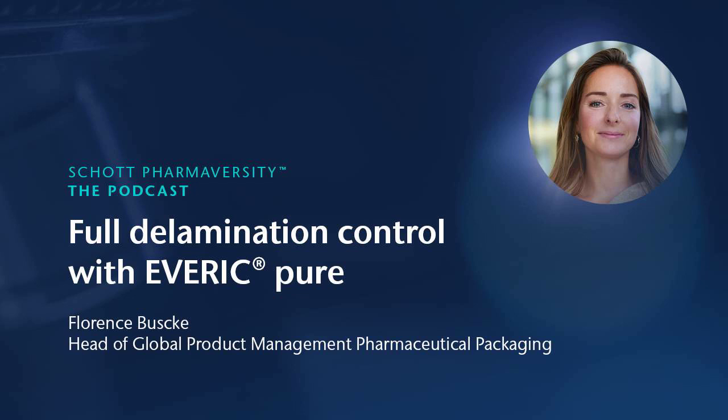And you have seen today in our presentations and publications, we show leachable studies. That means that in this case, we conduct those studies with buffers and not only with a solvent like for the extractables. To go deeper, leachables are compounds, or in our case elemental ions, that migrate from the container, or if it's a system, also the closure system, under normal, as I said, in-use storage conditions, and to which a patient can be exposed during the intake of the drug. So it is very important to always have this link.